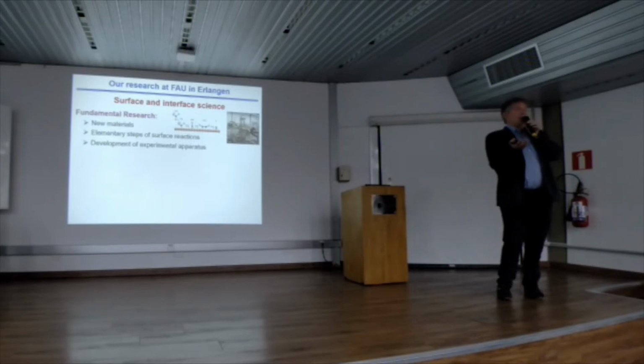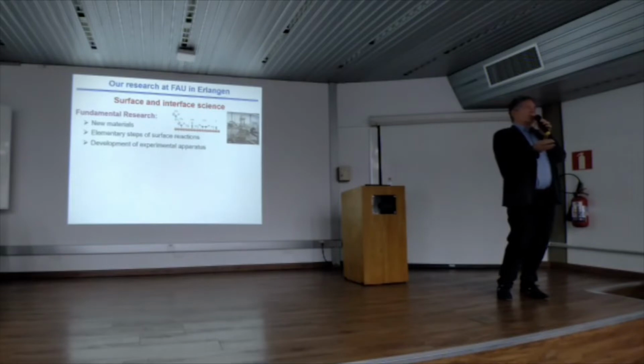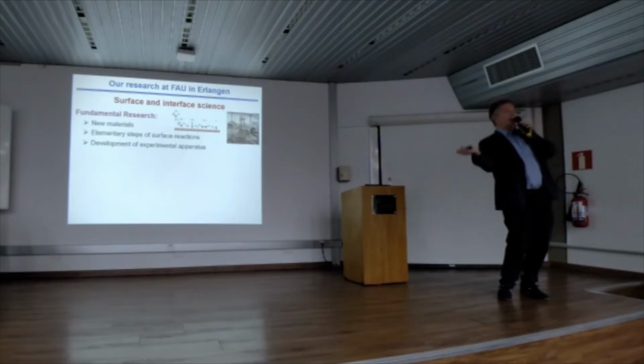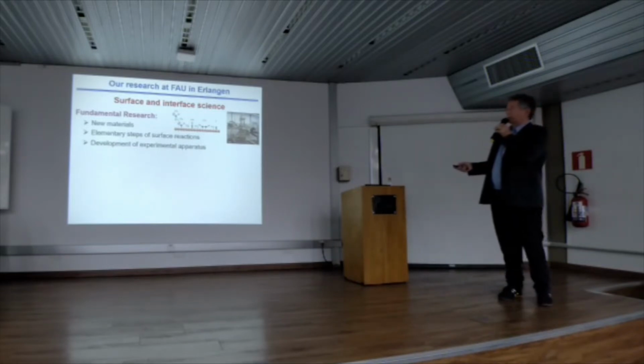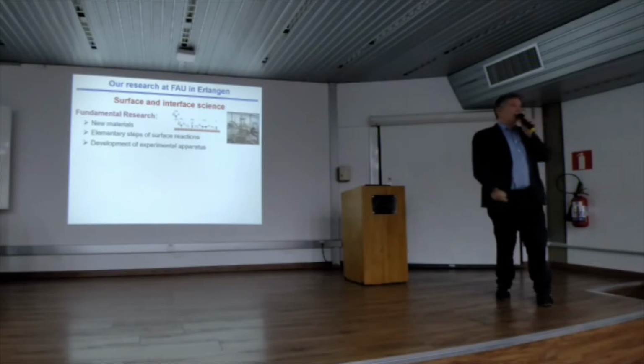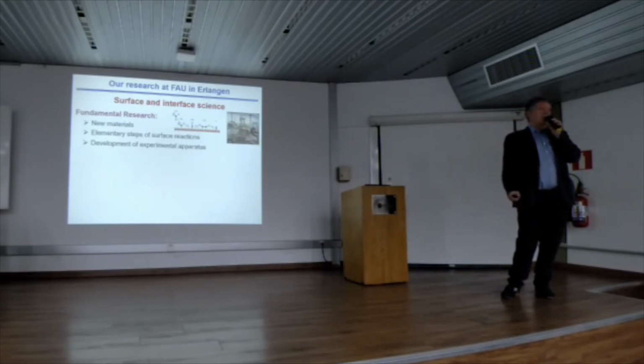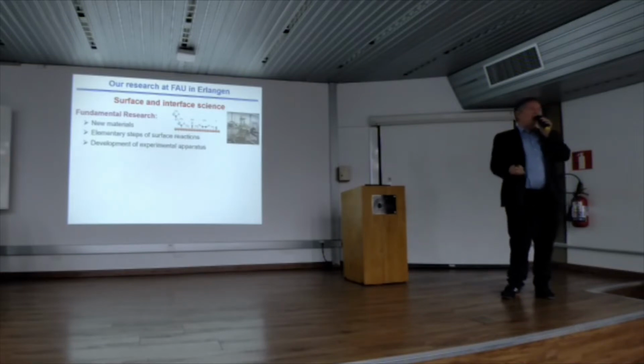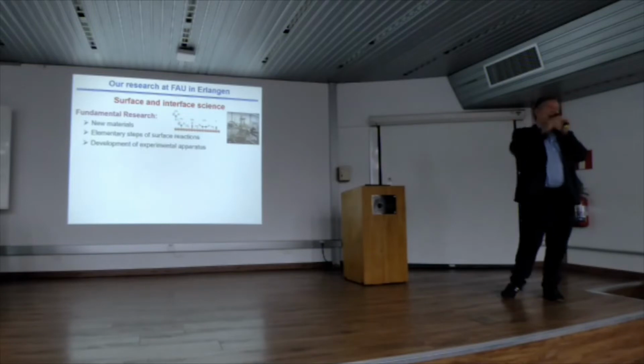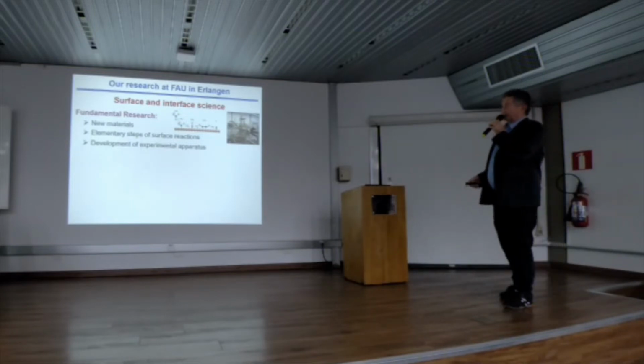But a liquid is a liquid, and if you want to do an angle resolved measurement and you tilt the sample, the liquid is gone. So the question is, what can you do? You can rotate the analyzer or use two analyzers. That's the cheapest solution. This is only 100,000 euro, but all other solutions are close to 200,000. If you have a rotatable analyzer, that is pretty difficult.